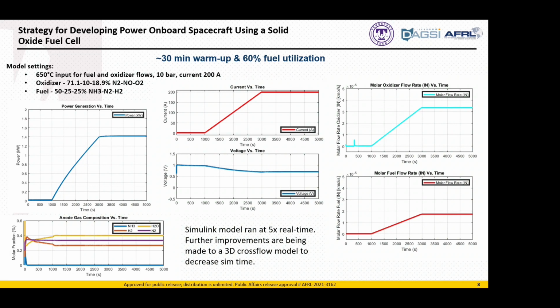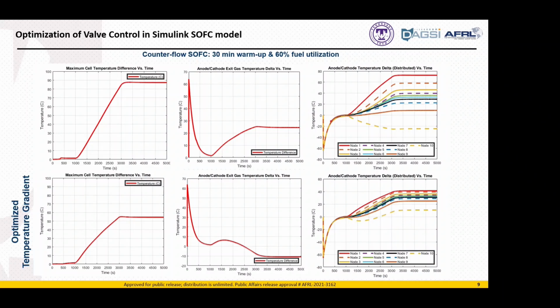This is at a set fuel utilization here. You can see the initial warm-up here in these graphs and the respective current voltage profiles, as well as the fuel and oxidizer flow rates. And then one thing that we can do with this type of model is we can optimize the control in order to meet certain targets. So one of the things that we want to do for these high temperature solid oxide fuel cells is we want to minimize the temperature difference across the cell. And so this is a planar fuel cell stack, but with a counterflow flow orientation to it. So the anode fuel and the cathode oxidizer are flowing opposite to one another.